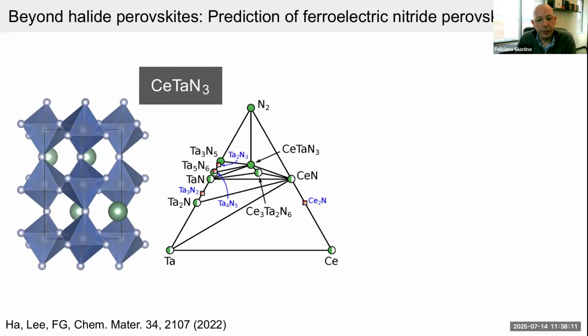So the interesting story in this work that was from 3 years ago is that when we sent it out for review, we got a lot of pushback from the referees and even from the editor because they told us that this compound would require cerium to be in the +4 oxidation state, which is next to impossible because nitrogen has to be -3, so this would be -9, tantalum is +5, so the cerium would have to be +4, but it usually likes to be +3.